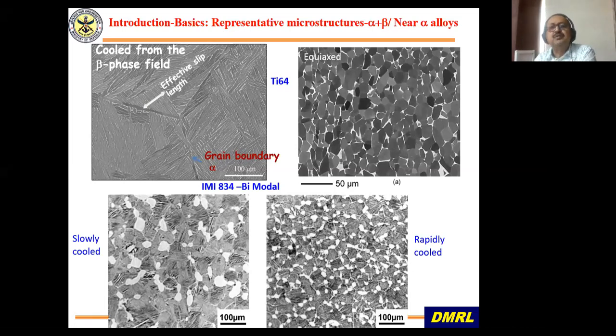Whenever you have a superplastic application, you can see you have very fine grain sizes as compared to this, where grain sizes are pretty large. Here you get much finer grain sizes, and the two phases are distributed almost 50-50, and so that is where the superplasticity kicks in. Then the next two structures are of near alpha titanium alloys, and this is what is known as bimodal structure. This is very important.